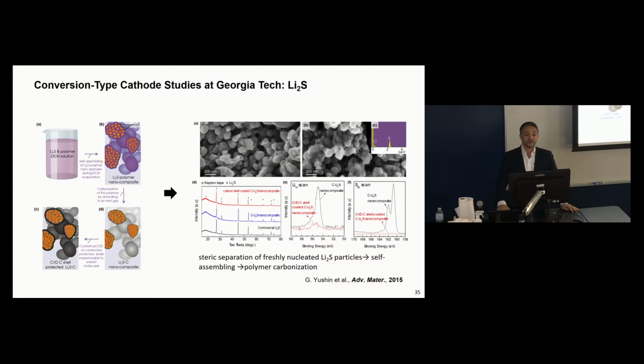So effectively, we found that lithium sulfide can be dissolved in ethanol and methanol, some organic solvents, to a decent degree. And if you have, let's say, a polymer that can also be dissolved in the same solvent, and you simply dry the solution, at some point lithium sulfide will start precipitating, right, as nanoparticles, homogeneously. And then, because if you use a polymer which has polarity on the surface, and lithium sulfide is polar, you're going to get coatings of the polymer on the surface of lithium sulfide, right? It may prevent ripening of the lithium sulfide particles, crystallization to larger sizes, which we want to avoid. And so then at some point you will form these clusters of lithium sulfide nanoparticles within this polymer matrix. And because lithium sulfide is thermally stable, you can carbonize it, right? And you can produce lithium sulfide nanoparticles embedded in these carbon composites, elastic carbon composites, which you can further protect with the shell.